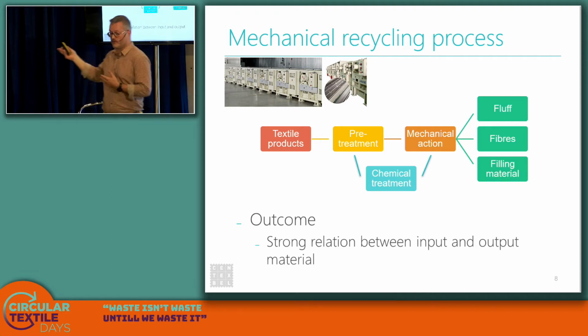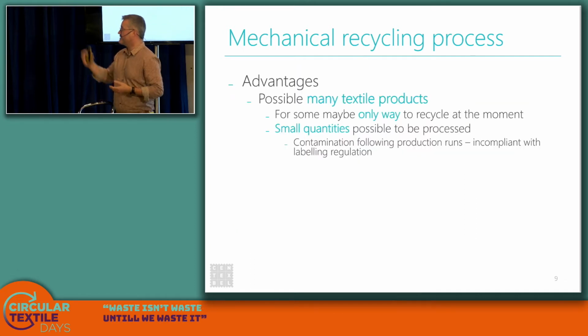The outcome: there's a very strong relation between input and output. If I put a garment in there, remove the buttons, from a fabric that has been washed over 100 washing cycles, consisting of cotton and polyester fibers, the cotton is completely destroyed due to the use and the washing, and you will have cotton dust, but the polyester fibers remain, and you can spin with those fibers. So there's a direct relation between what you throw in and what you get out. So if some companies claim that they can have as an output 90% of the textiles you put in that are spinnable fibers, it's not always the case. We doubt those claims.